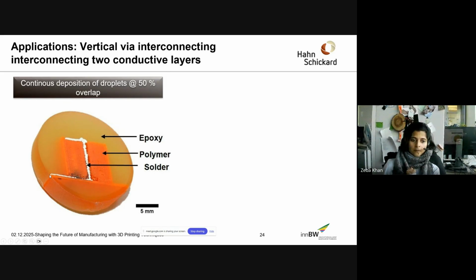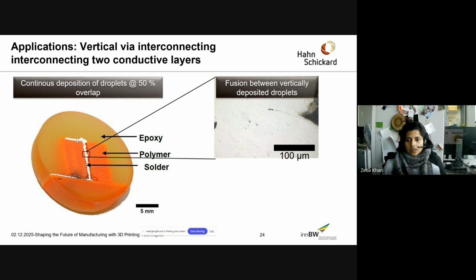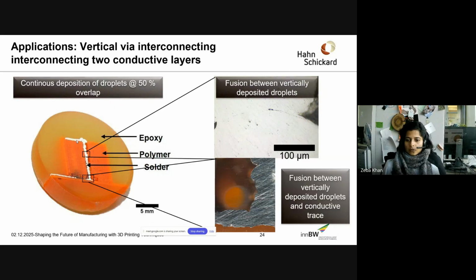As mentioned earlier, we print the substrate, we print the metal conductive trace, then we print one layer of polymer with the hole, we print the metal, polymer, hole, metal. So this was really step-by-step processing of additive manufacturing. And with this, you can see here how the fusion between the vertical droplets looks, and also how the fusion between the bottom part of the traces looks.